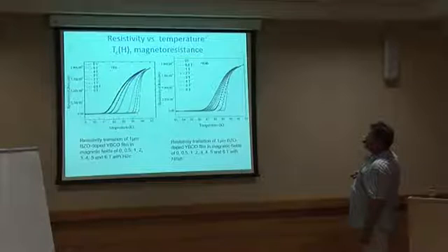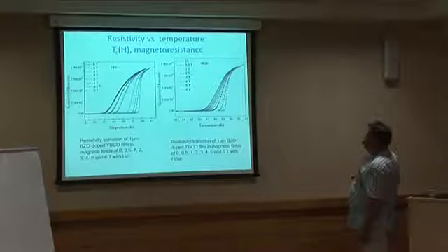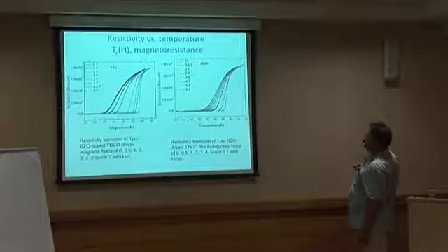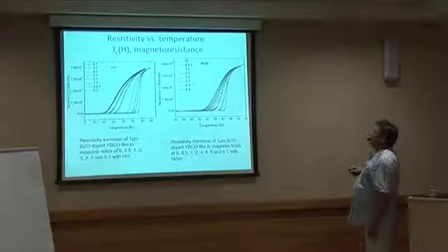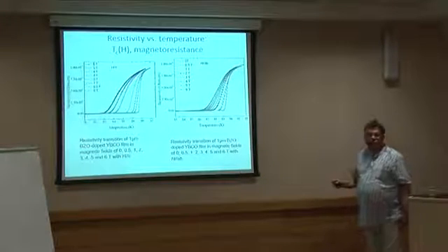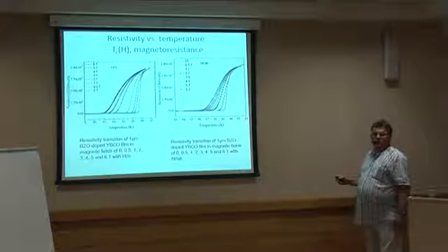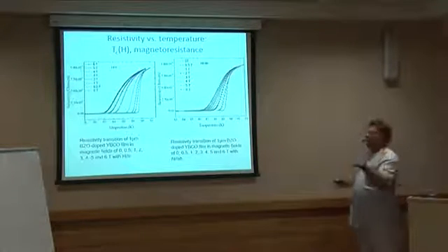You see that Tc, from the onset, but let's talk about this one, goes from about 89 to 81 at 6 Tesla for field parallel to the z-axis. And for field parallel to the ab plane, we go from 89 point something to 86. So you see that for this type of fields, the superconductivity at these fields is better along the ab planes.